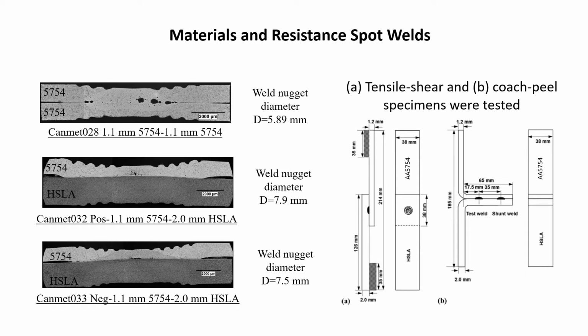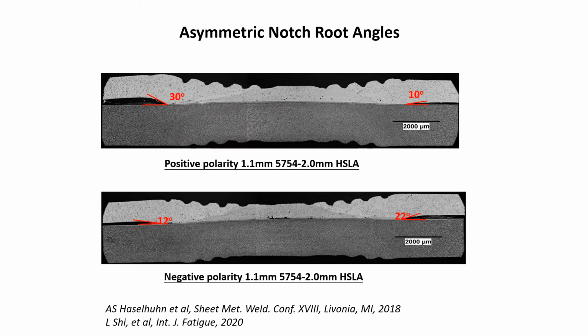The left three figures are macro cross-sections of AA5754 aluminum alloy to itself and aluminum to HSLA steel, with aluminum connecting to positive electric polarity and negative electric polarity. The weld nugget diameters in aluminum to steel spot welds are around 7.5 mm, which are larger than that of aluminum to itself. From the cross-section views, we observed that asymmetric notched angles formed in aluminum to steel stack-ups regardless of polarities.